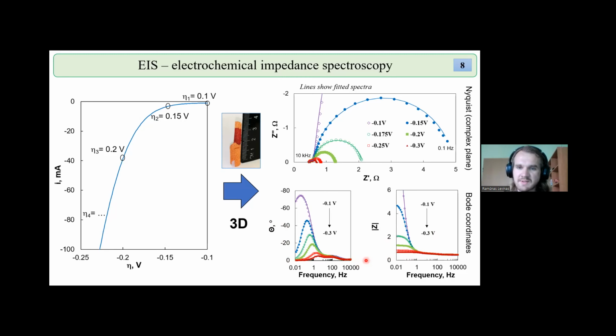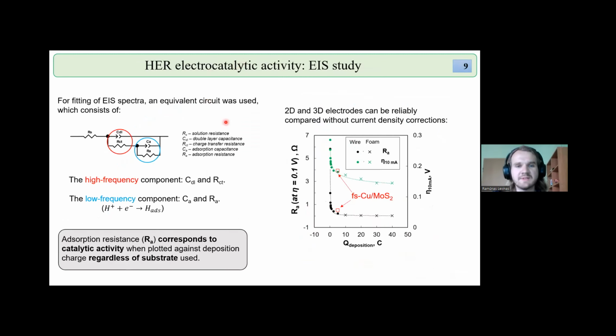And the results are interpreted by equivalent circuit fitting. So in this case, the present circuit was used, and the circuit has two important components apart from the electrolyte resistance. So the high frequency component, which is comprised of double layer capacitance and charge transfer resistance, and more importantly, the low frequency component, which is comprised of adsorption capacitance and adsorption resistance. Precisely these two parameters limit the current electrochemical reaction.